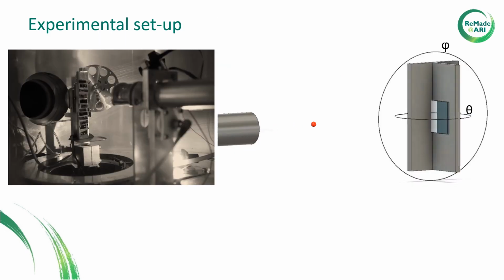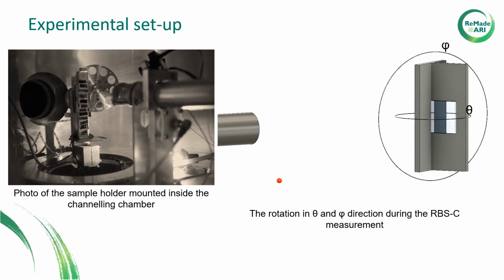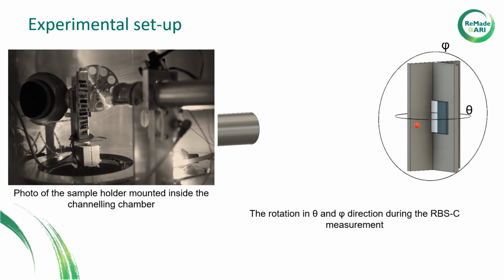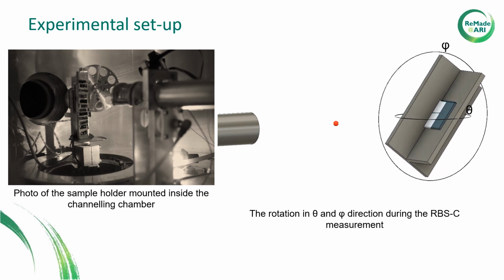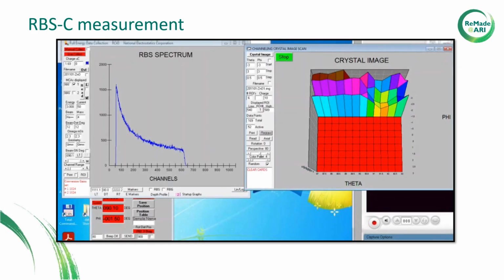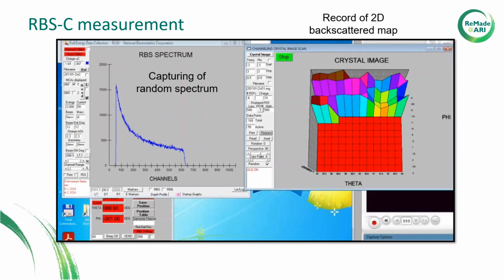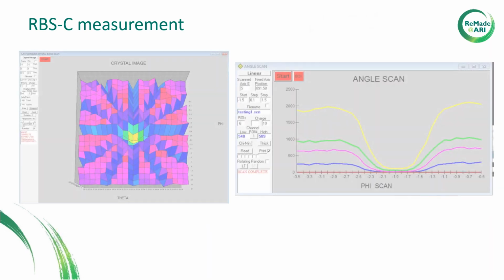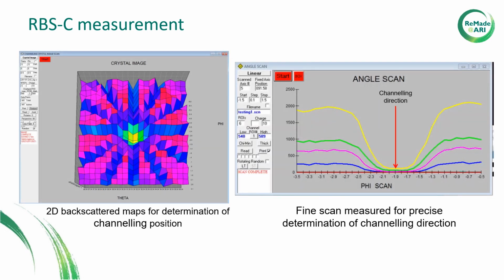The sample holder with the crystal is mounted on the goniometer, which allows us to rotate the sample at precisely defined steps in two directions, the theta and phi axes. During the measurement, we rotate the sample in precisely defined regions, and we gradually capture spectra of backscattered yields in each defined position. These spectra are integrated into one, which gives us the random spectrum for the chosen crystal sample. Simultaneously we obtain a 2D map of backscattered yield in connection to crystal rotation, which provides us with the position of the channeling direction. The position is then specified using a fine scan measurement with angle variation with a small step.